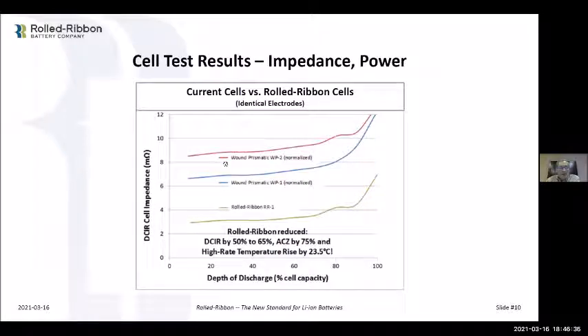And then we put them through the same torturous test that you can imagine exists for a directed energy weapon, high rate discharge. And what you see is that the DCIR for the rolled ribbon cell reduced, you can see the DCIR here, we reduced the impedance by 50 to 65%, depending upon which one of these you want to use. The ACZ was reduced by 75%, and the high rate temperature rise was reduced. That's not shown in the chart here, but basically the rolled ribbon cell was 23.5 degrees cooler under the exact same load, the same working profile. Basically, it rose by about 10 degrees C, and the wound prismatic cell rose by about 33.5 degrees C, which actually took it into decomposition zone. Again, this is a high stress test.